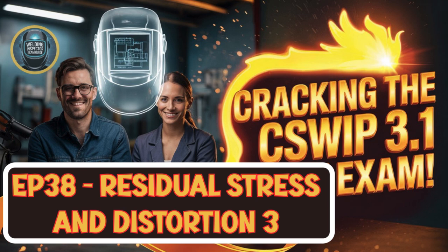Well, generally speaking, MIG-MAG welding, because it has a high deposition rate and you can move quickly. Right, that's often preferred over something like manual metal arc, MMA, stick welding. Because MMA is slower, stop-start. Yeah, you're changing electrodes, interrupting the heat flow. It's just inherently a slower process. And gas welding, like oxyacetylene, typically produces more angular distortion than the arc processes. More. Why is that? It's mainly down to the heating. It's slower and the heat source is more diffuse, spread out over a bigger area for longer. So the metal has more time to soak up heat and, well, move around. Pretty much. More time for expansion and then contraction, leading to more bending.